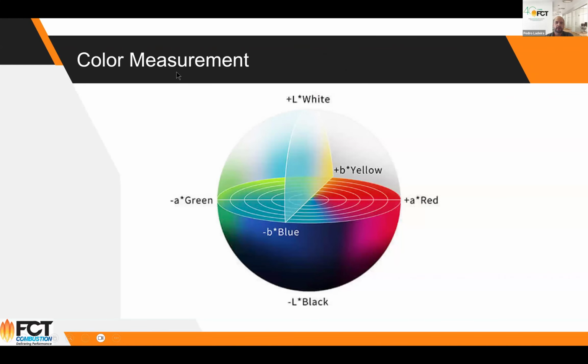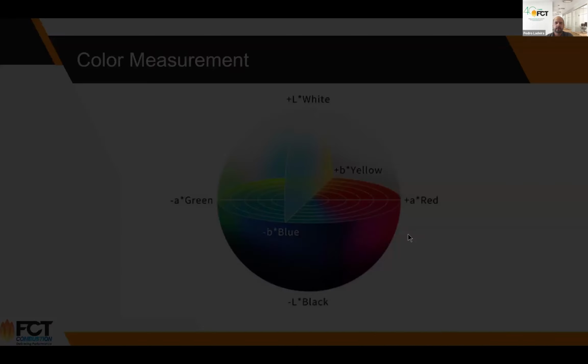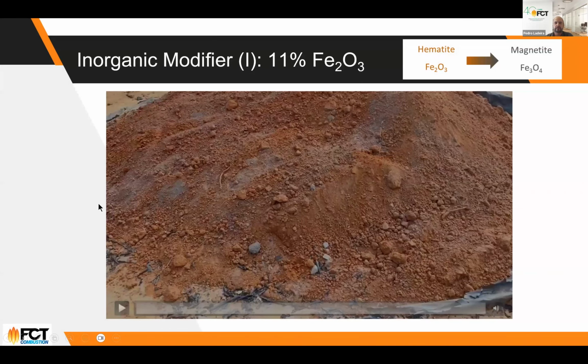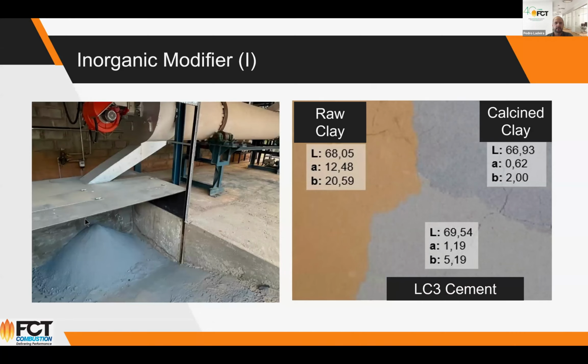What you can see here, and I have to mention that the way we measure color is a system of L, a, and b. So just to make it simpler, the a color should be as close to zero as possible. We try to get to 2.5 a color, so reducing the redness of the material. So we want to measure how the color a behaves. As you can see here, this one should give you about 10 to 15 a color. And the results we get from the experiment are, starting with a clay with a color a of 12, we can reach easily less than 1 by introducing limestone to the mix and co-feeding it to the kiln. And the LC3 cement becomes fairly gray, as we want it. So this is just an experiment done in a pilot plant.